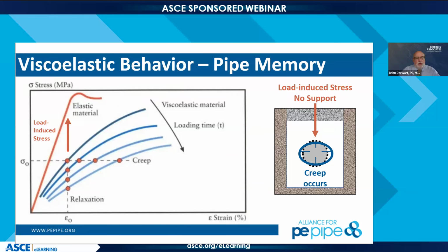Viscoelastic plastic materials, and it's not just HDPE, you can look at rock salt. Rock salt's viscoelastic as well. It means it's going to creep. And the creep will cause that elastic curve, instead of being straight, to start bending over with time. So you're stretching on it. The modulus which we use for design, you want to take into account the creep, and the modulus in the charts does take into account creep. It's part modulus of the material, and it's part creep.